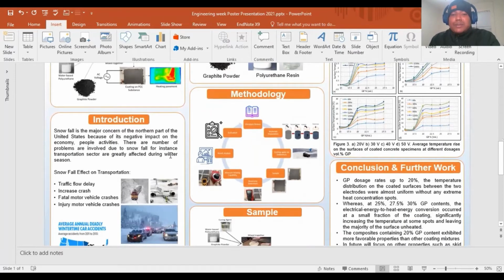This research goal is to investigate the viability of using water-based polyurethane and graphite powder composite as an electric conductive coating for constructing heating pavement. The synthesized composite is applied on the top surface of the Portland cement concrete pavement. The optimum amount of GP dose is determined by using percolation threshold theory to achieve the desirable resistive property of the electric conductive coating. The heating capacity of the conductive coating is measured with an infrared thermometer by maintaining controlling parameters.